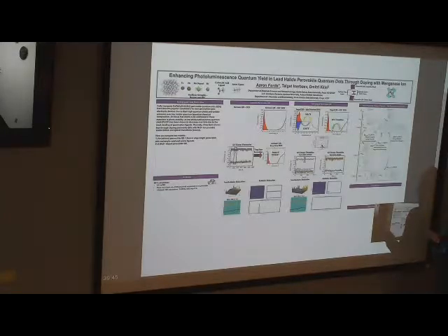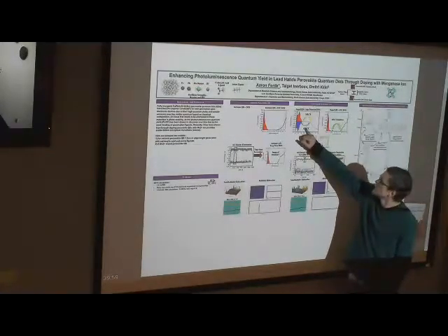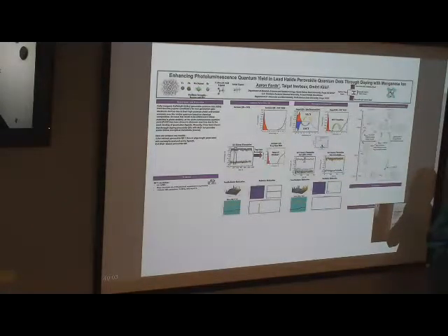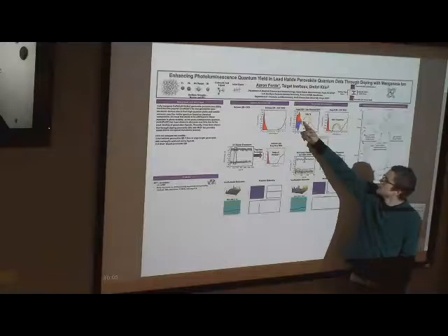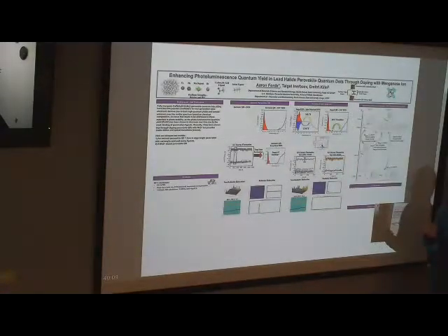It's a spin 5/2 ground state, and we applied a spin polarized density of states for this, and we find that the manganese dopants introduce two states within what you normally think of as the traditional band gap of the perovskite quantum dot.